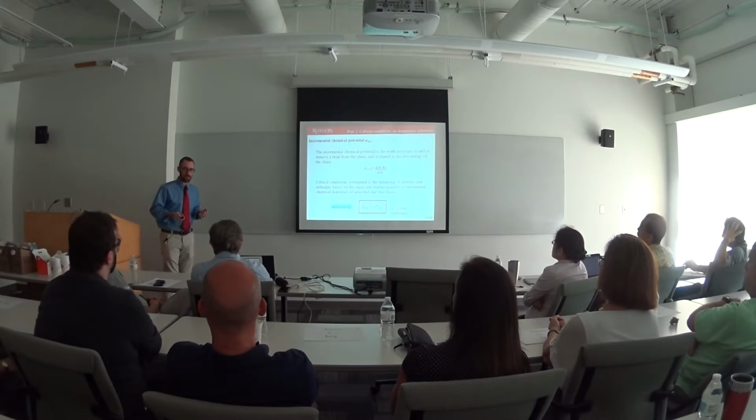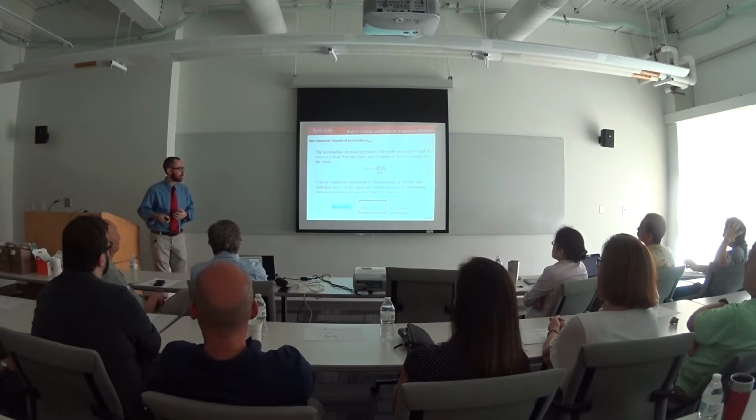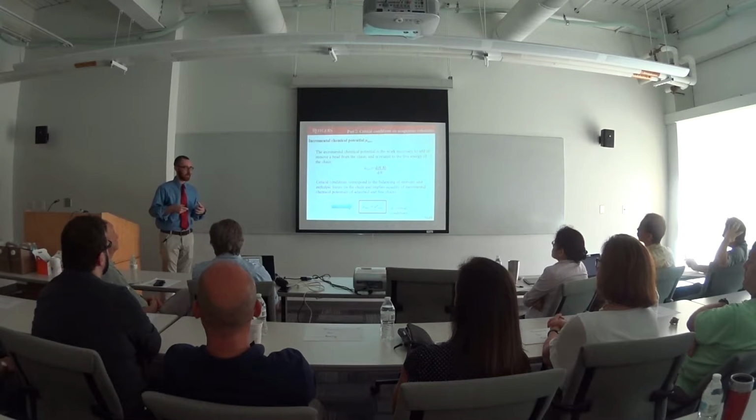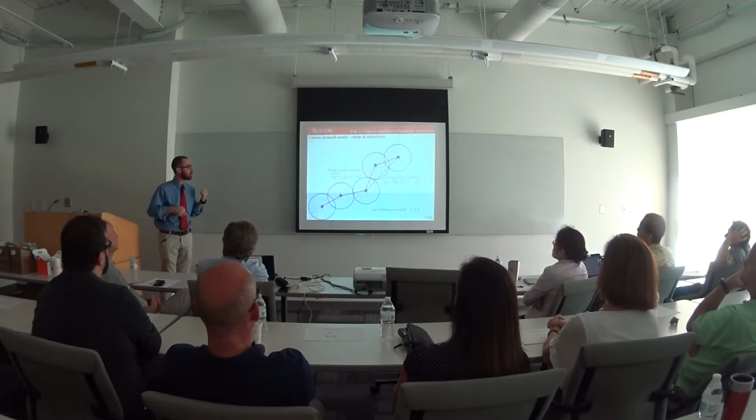The critical conditions of polymer adsorption correspond to the balancing between the different effects on the chain, both enthalpic and entropic. And it implies that we have the equality of our incremental chemical potential for both adsorbed and free chains. So this is our new critical condition that we described thermodynamically.